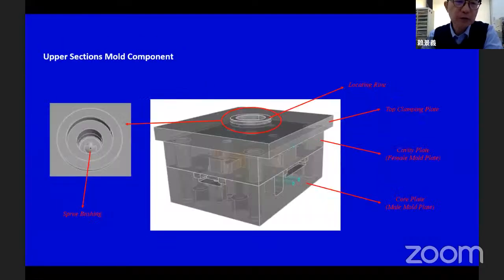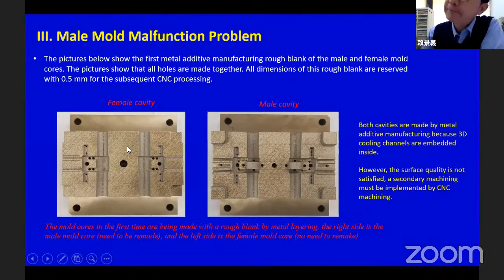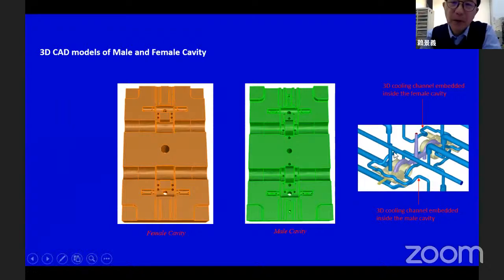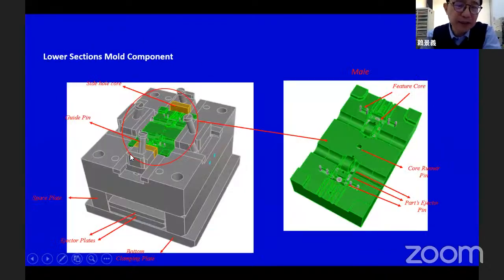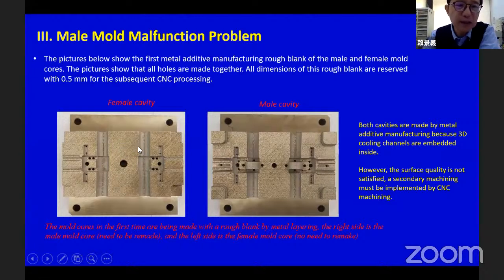Those 2 parts, each costs around 5,000 US dollars, which means that if we add the 2 together, it costs about 10,000 US dollars. Once we fabricate the part, we also need to fabricate the mold base, and we also need to perform secondary machining. As you can see here, the surface quality is not so good, so we need to perform the secondary machining.